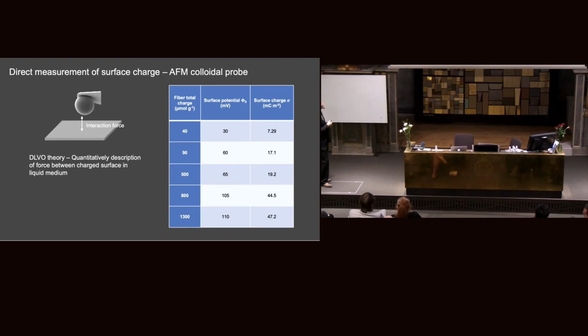Using the DLVO theory to fit this force curve, we can get the surface potential. And using the Poisson-Boltzmann equation, we can calculate the charge on the surface. So we can see after this process, the charge is still increasing, from 7 to 47 millicoulombs per square meter.